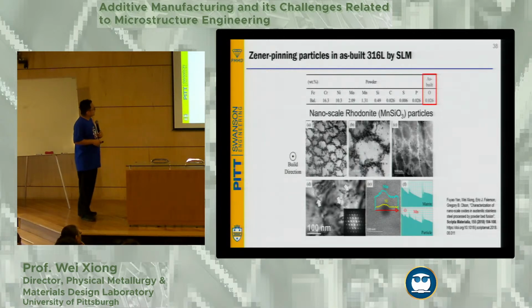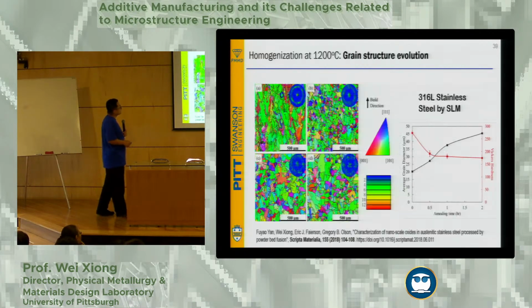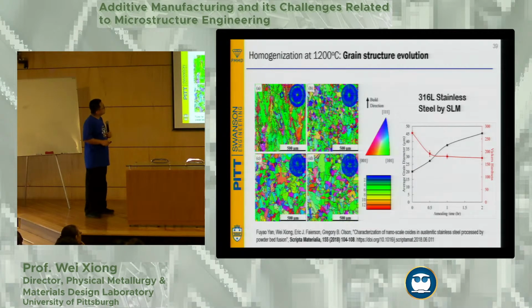So we started with this homogenization again. We finished printing, then did high temperature processing with homogenization at 1200 degrees C, austenizing it. Then this is continued with different examples - we did the printed one, with half an hour, one hour, and two hours.